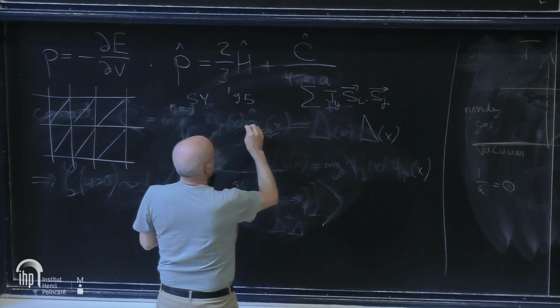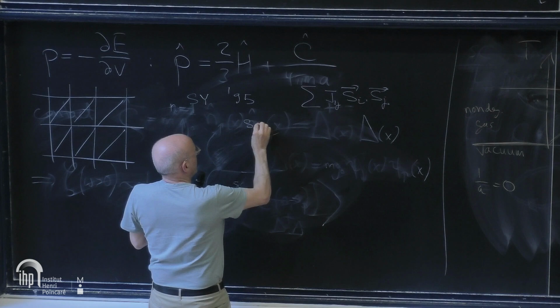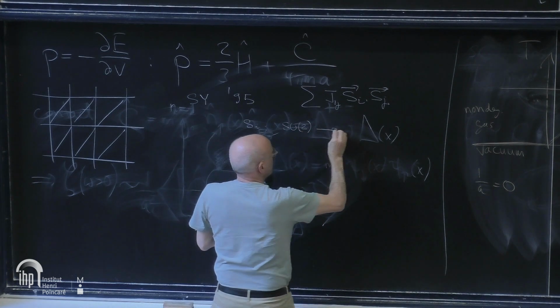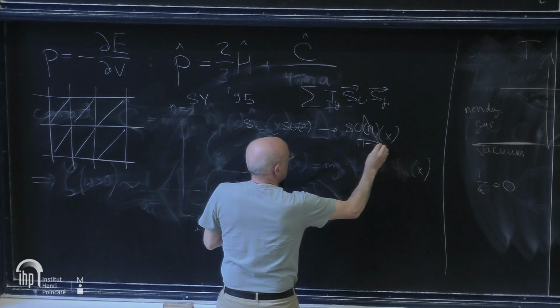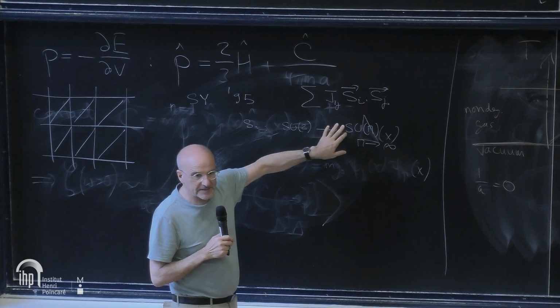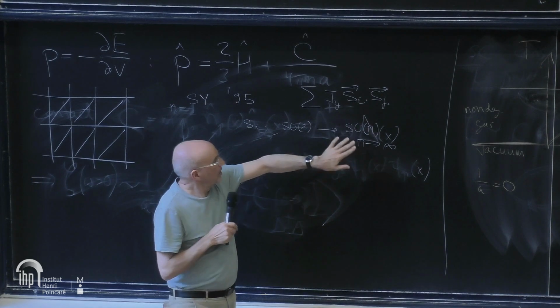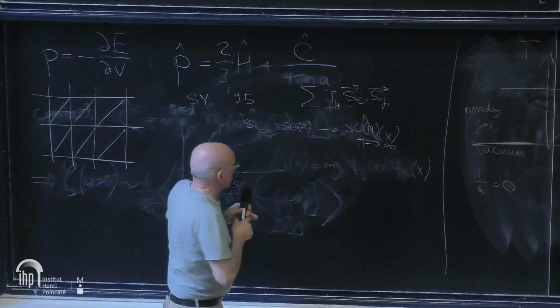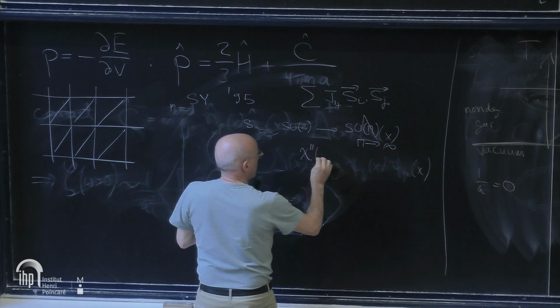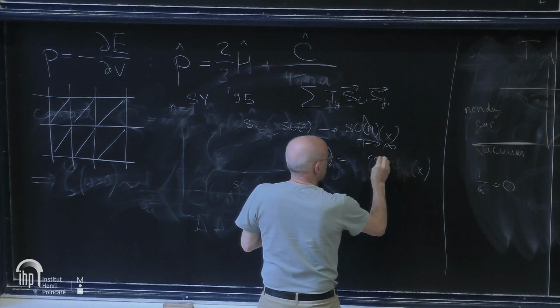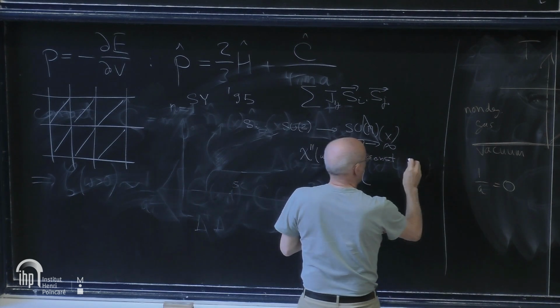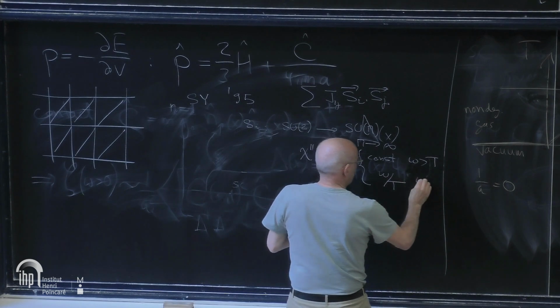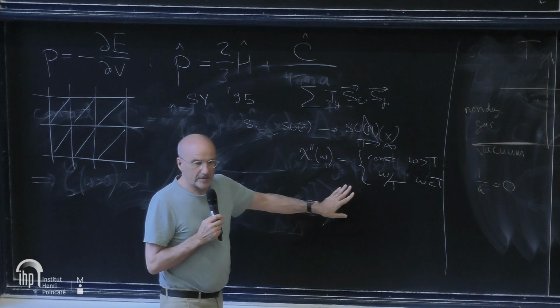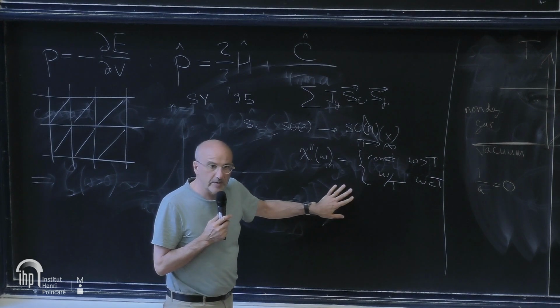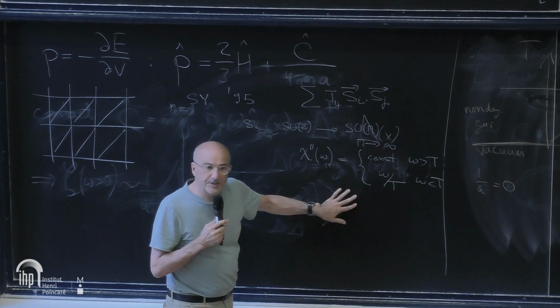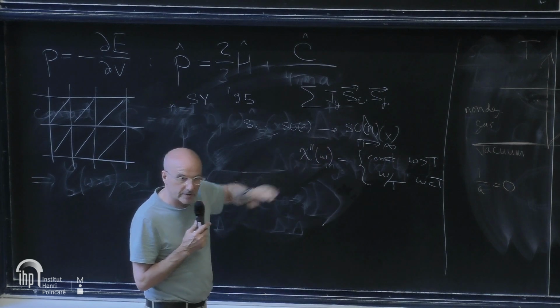But in fact, what Sachdev-Ye showed is that if you extend the spin from an SU(2) representation to a representation of SU(M) in large M, the quantum fluctuations destroy the spin glass phase, and this model actually is a spin liquid, right, with spin dynamics which is actually chi double prime of omega equal constant for omega larger than T and omega over T for omega smaller than T, which is exactly what has been proposed phenomenologically as the marginal Fermi liquid to explain some of the phenomenology of the strange metal. Okay, however, this is purely a model of spin.